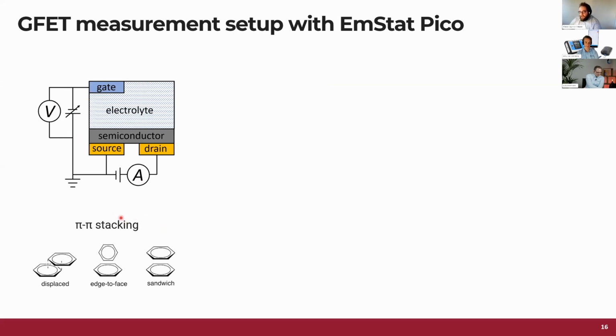In this experiment, we're showing how the pi-pi stacking on top of graphene works. Pi-pi stacking is a method of surface modification, or maybe like interaction, where we use the conjugated pi electrons from aromatic rings, for example, that interact with each other and then allow for kind of stable, more stable bonding. For that cause, people have very often been using pyrene derivatives in here. This is pyrene butyric acid, which gives us the COOH groups on the surface of graphene.